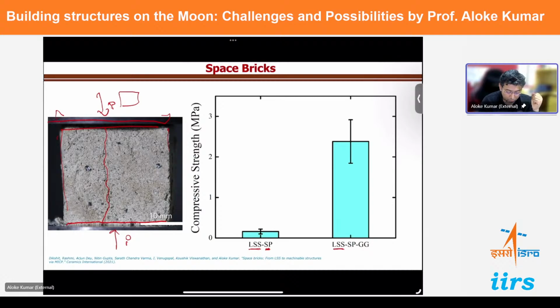Now we added on the lunar soil simulant, we had the bacteria now, and we added this bit of a guar gum, right? And when we tested that, we found that the compressive strength was of the order of 2.5 megapascal to almost 3 megapascal. Now, just to put this into perspective, ice is of the order of 5 megapascal, sometimes higher, depending on the temperature, around 5-6 megapascals. So 2.5 is not bad. It's almost like half of ice. And with ice, you can make igloos, right? So what did we learn about gravity on the Moon? It's 1/6. So this compressive strength is good enough to start making houses with this kind of bricks.